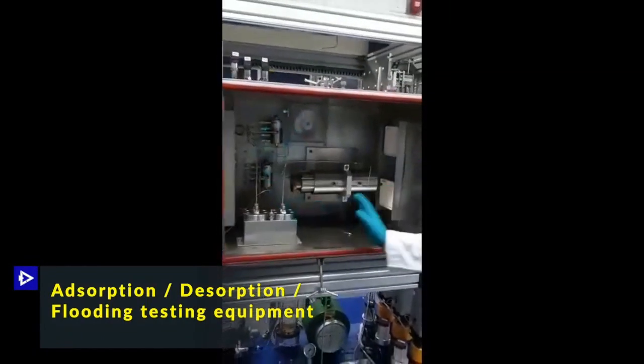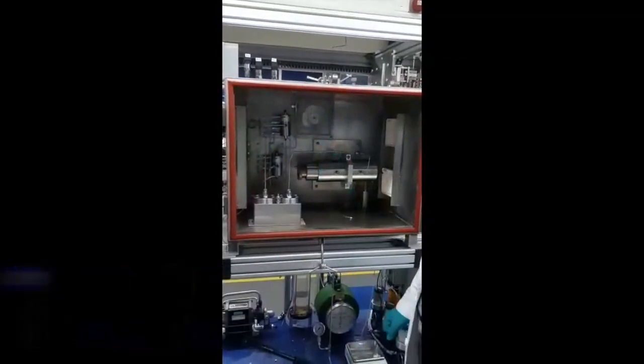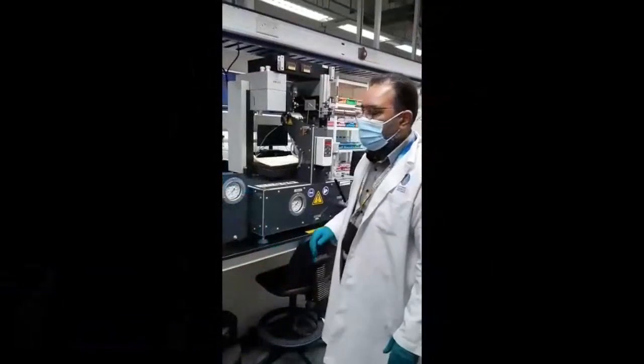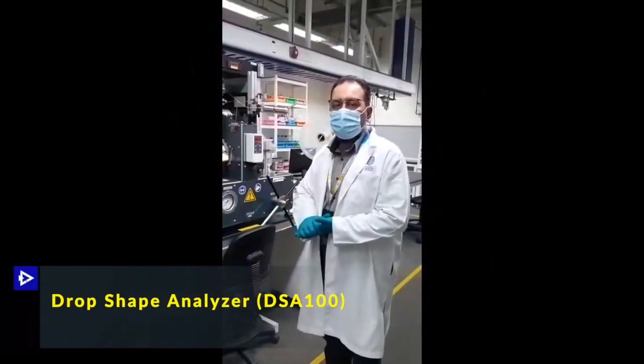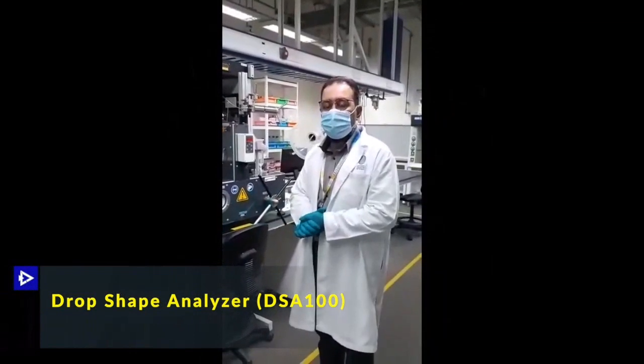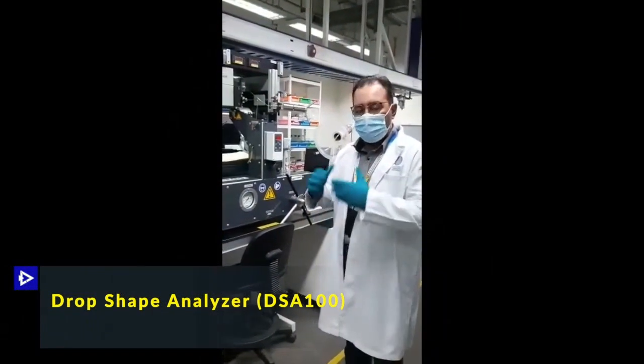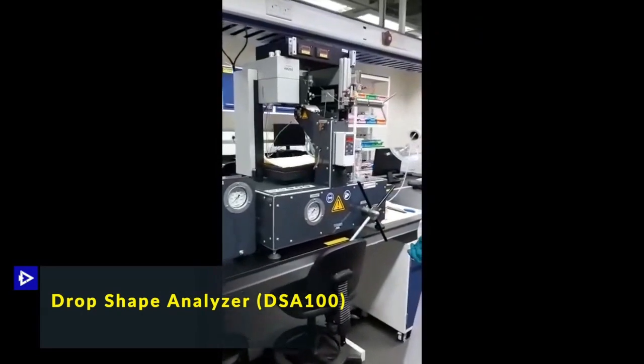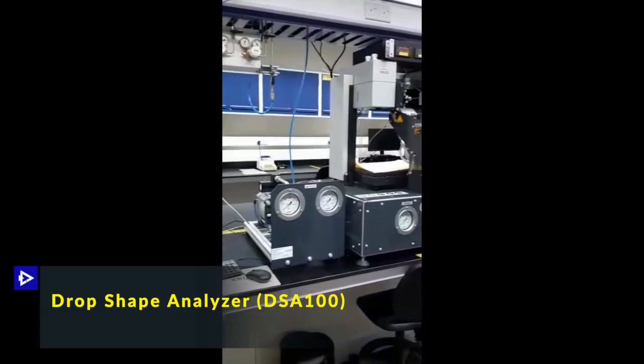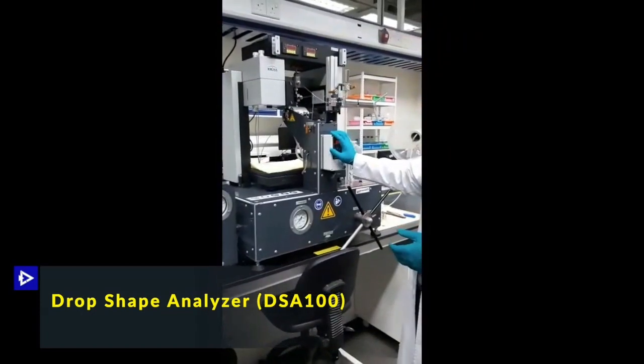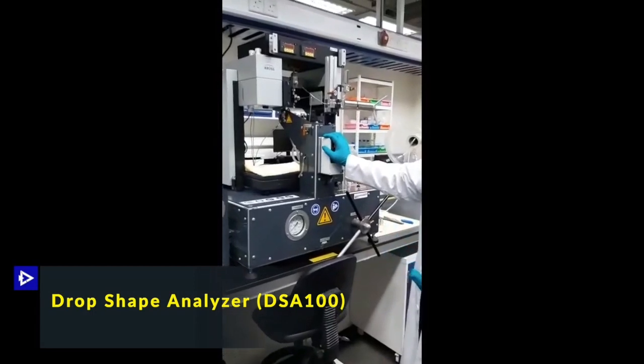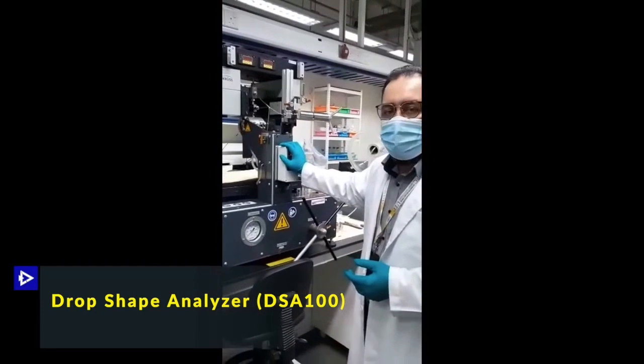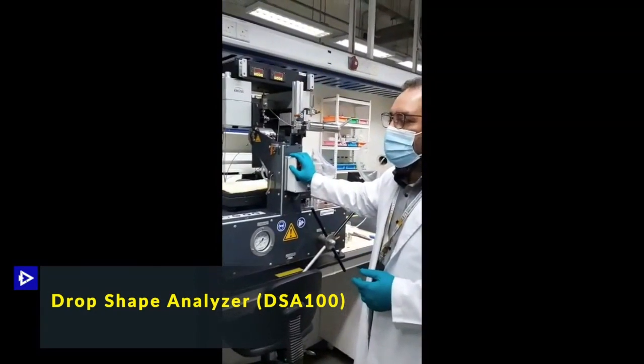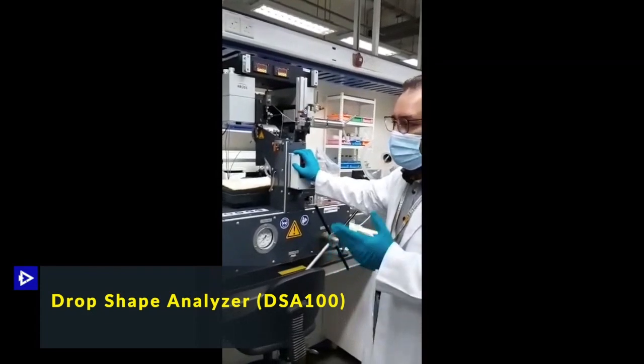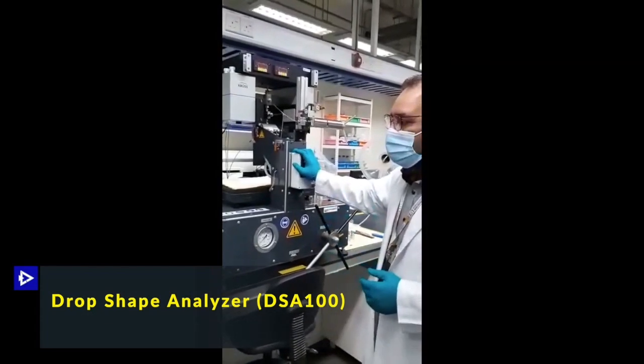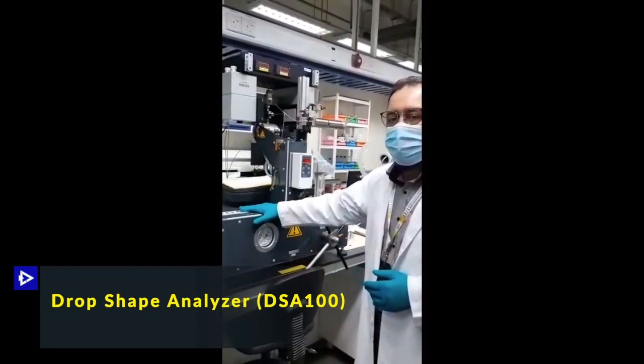And here is the heating system that we have, with a fan to distribute the heat at 80 degrees. The DSA 100 measures the contact angle, interfacial tension, and some of the other physical properties of the shale material, and some other porous materials that we have. In this equipment, we can go up to different temperatures, up to 60 or 80 degrees, and also very high pressures, such as 300 bar, 30 megapascal, or even slightly more. It is a very unique piece of equipment, and it is iconic for studying physical properties of shale and porous material all over the world.